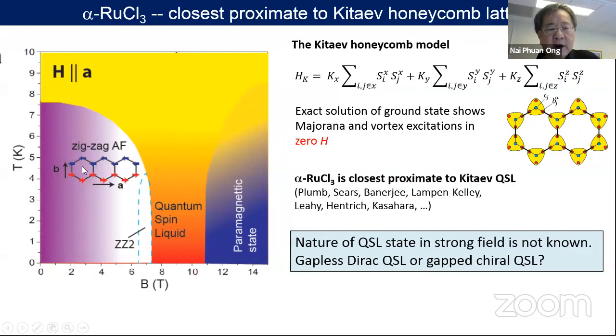So I will be using these two terms just like in graphene. The zigzag state is comprised of spins aligned along a zigzag direction, and they are anti-parallel between zigzag lanes. And there may be a minor phase slightly different from this here. But then above 7 Tesla in plane, parallel to the A-axis, you kill this order, and it's thought that this is now a frustrated spin liquid phase, right? There are no magnetic Bragg peaks here, and lots of interesting thermodynamic signatures.